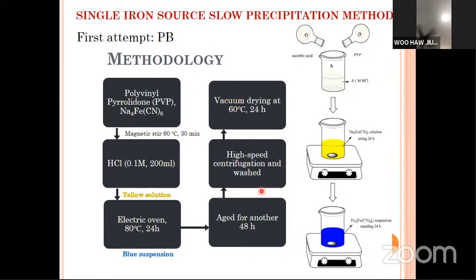This is our work. We prepare this material using a single iron source slow precipitation method. In our first attempt of preparing Prussian blue, this is the methodology. Basically, we add in all the starting reagents, mix and stir for 30 minutes at 60 degrees Celsius, and we obtain a yellow solution here. Then we keep it in an electric oven and heat it again for 24 hours at 80 degrees Celsius.